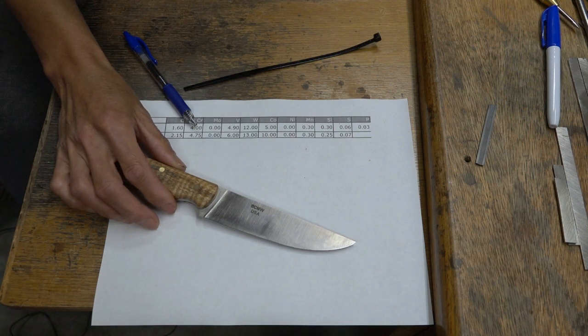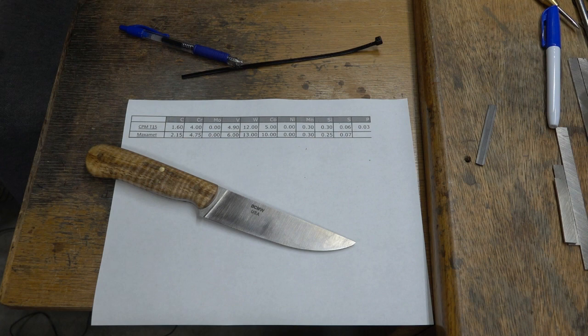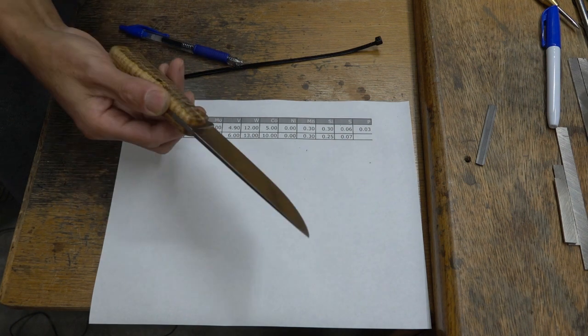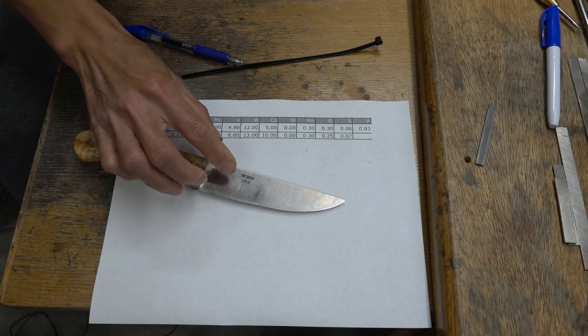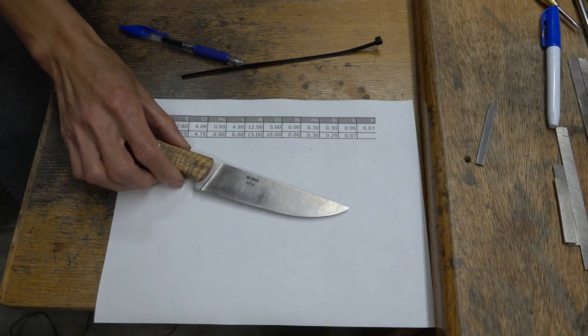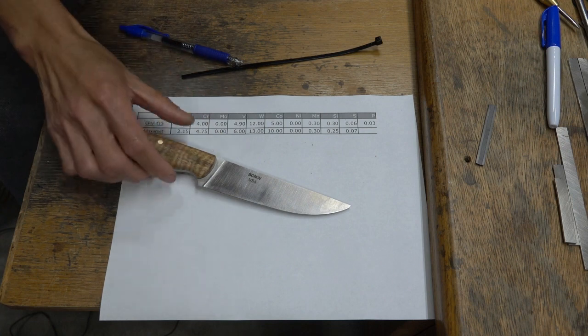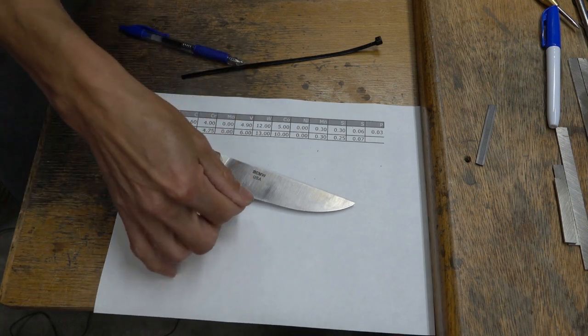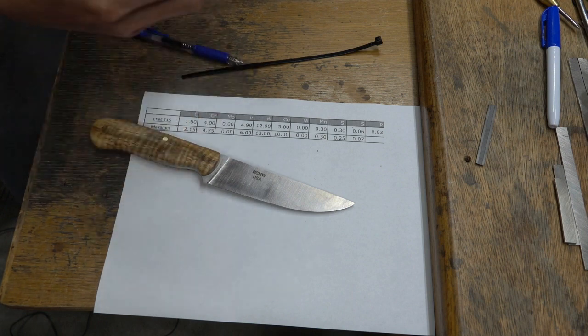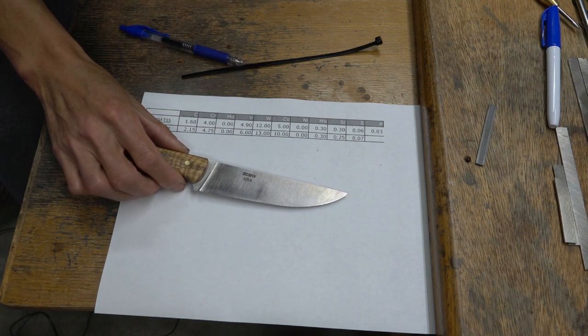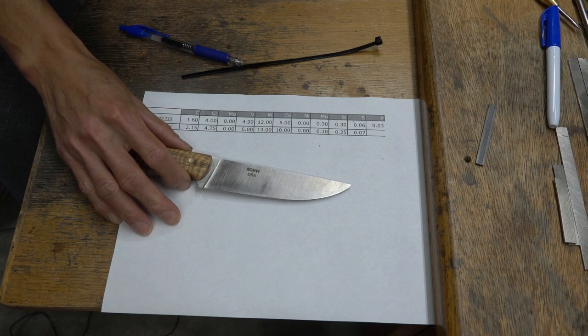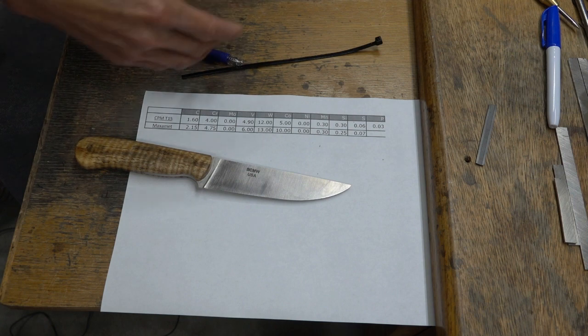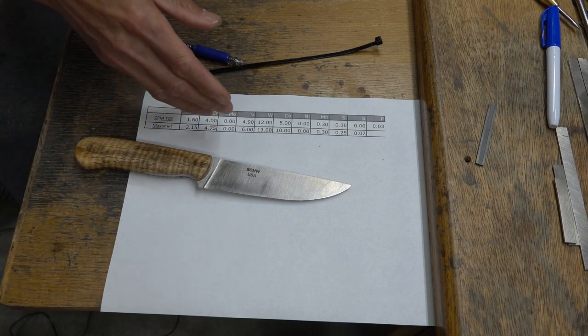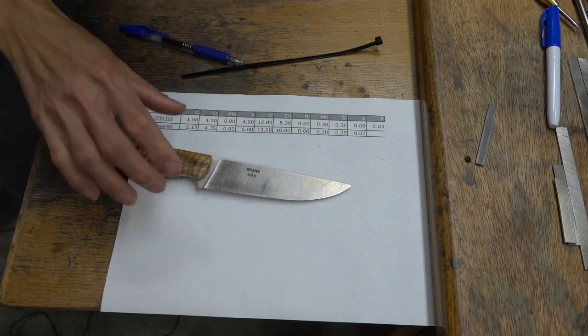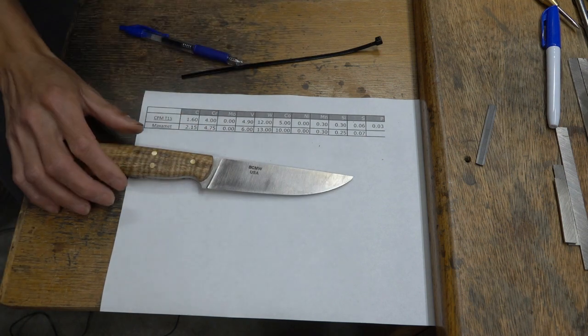I talked too long, and I got past the cutoff point. Basically, with this steel, if you're going to worry about losing the temper by mistake when you grind near the edge with some belt, and you heat it up, it has to be really, really hot before you mess up. It has to be totally red, and the steel dust is going to be totally off color. But of course, I always do one grind, dip in water and things like that, because I deal with other steel too.